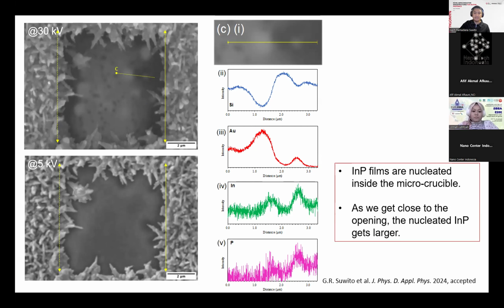But then, since gold has low solubility in phosphorus, if you check the phase diagram of gold and phosphorus, you would see that the solubility of phosphorus in gold is very low. And then we can associate that this indium and phosphorus signal is from a nucleated indium phosphide film.